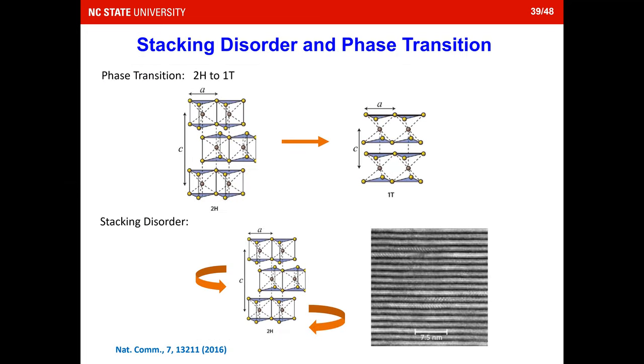So there are phase transitions during the charging process. There are also some stacking disorders, where the different layers have relative rotations that create disorder, and that can suppress thermal conductivity. Hopefully, within the next 4 to 5 years, we can find more disordered systems and suppress thermal conductivity more, so that you can achieve a large switching ratio to make a very good solid state thermal switch. So that is one approach we're trying recently.